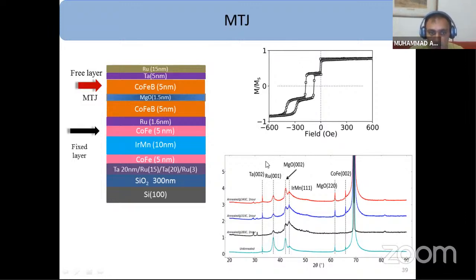Then I did the structure analysis of my magnetic tunneling junction samples. I have annealed my sample at 280 degrees for 1 hour. Then I have annealed my sample at 310, then annealed at 340 C for 1 hour. You can see MgO was grown as a 002 structure, which is considered basic for getting high GMR, high TMR values.